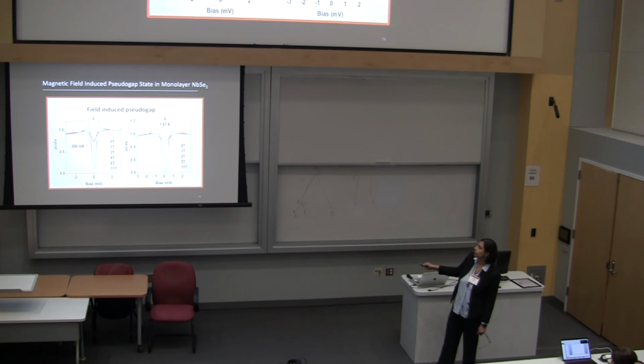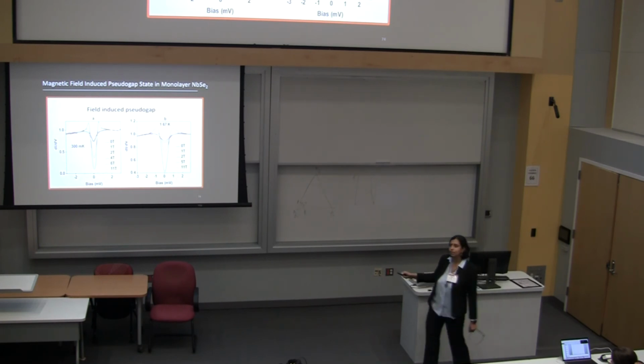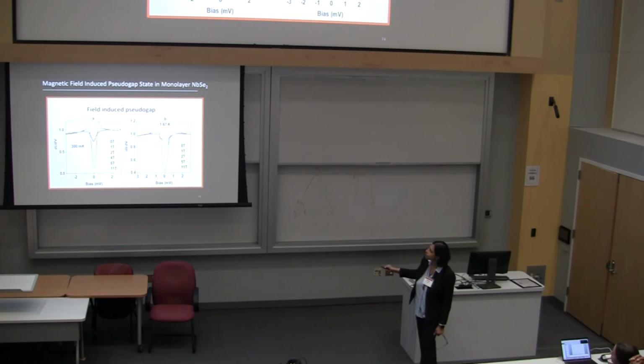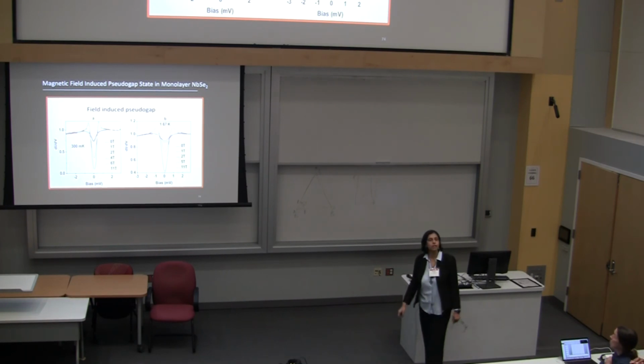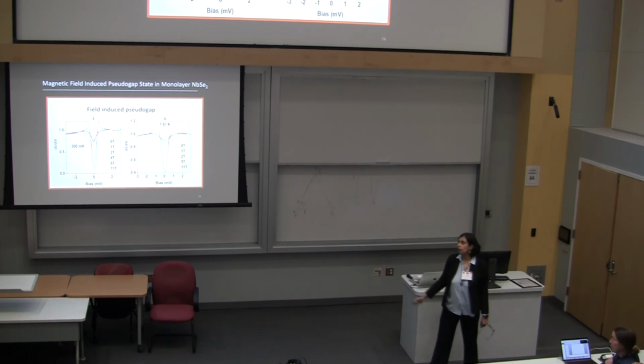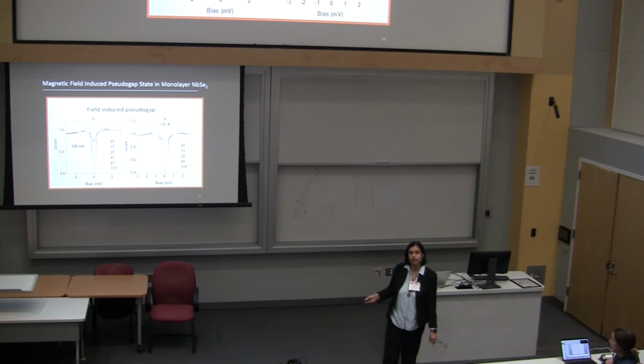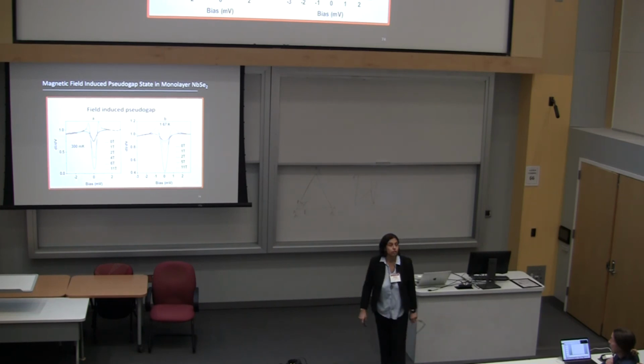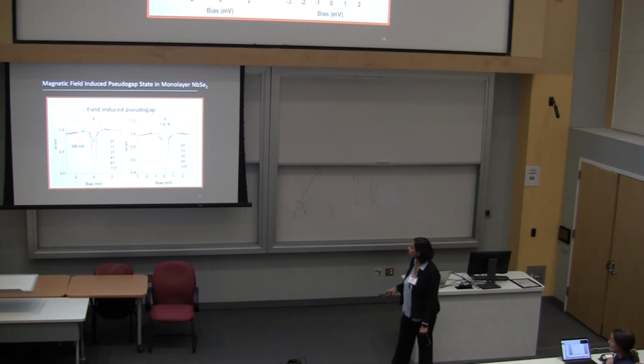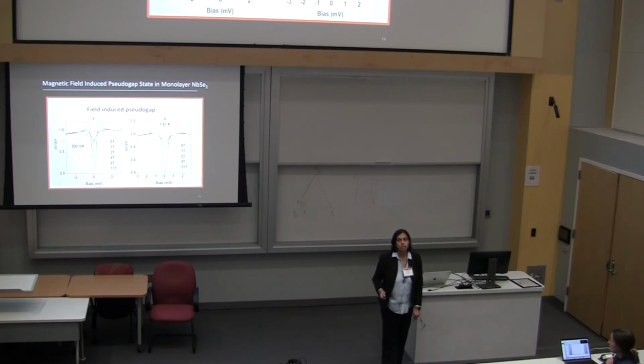Essentially, you end up with a pseudogap. And the magnitude of the pseudogap is very, very similar to the magnitude of the superconducting gap. Now, in bulk niobium diselenide, by now the superconducting gap should have disappeared. Certainly by 6 Tesla, the gap should have disappeared. So the question is, what's going on? And we see this pseudogap effect even at high temperatures.